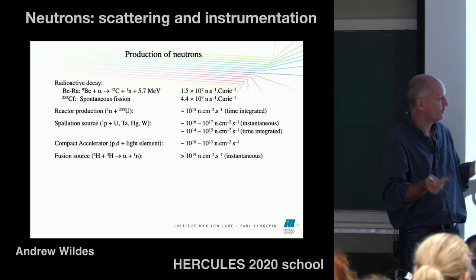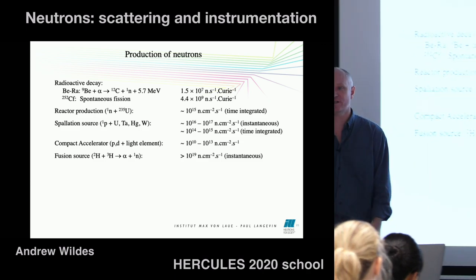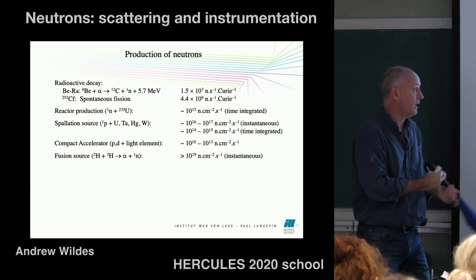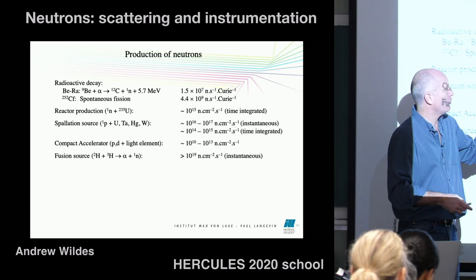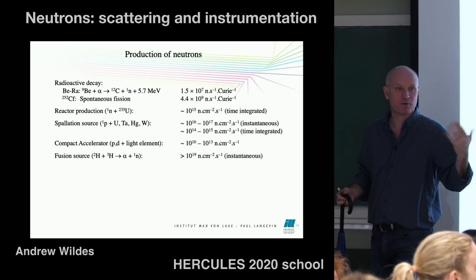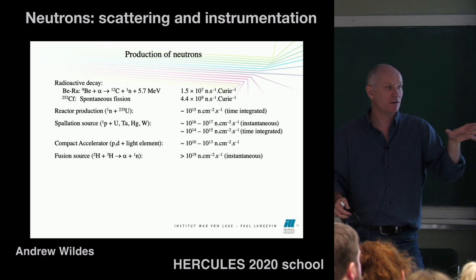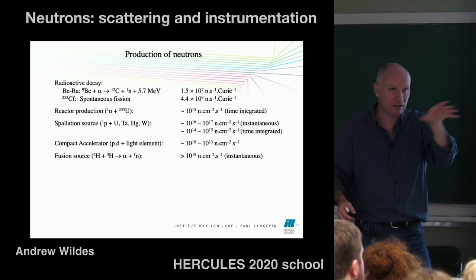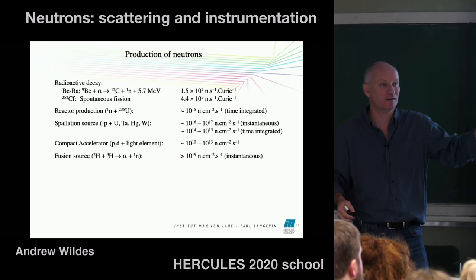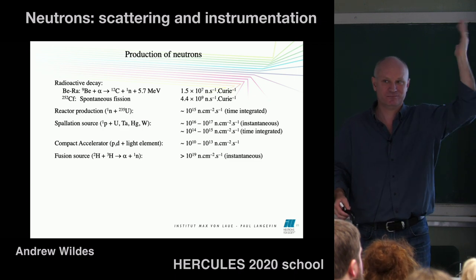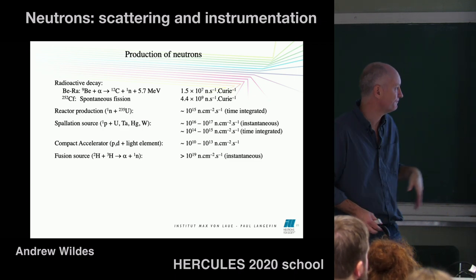So depending, again, on who you talk to, you're getting of the order of 10 to the 14, 10 to the 15 neutrons per centimeter squared per second, which is comparable to a reactor. The ESS is supposed to have of the order of the same integrated neutrons per second as the ILL, plus or minus a factor of two, something like that.